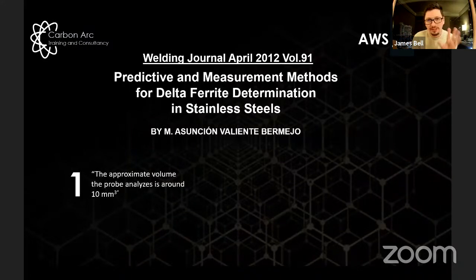And 3 things came out of this AWS journal, which were kind of a lifesaver to us and allowed us to really say what we're saying is real. It's not the way we're doing it. We're not taking our results and twisting them to fit a narrative we want to get a pass, but somebody else has seen this independently. So first one was that the Fischer probes produce an inspection bubble of about 10 millimeters cubed, which we could see because we did get a difference between thinner and thicker materials.